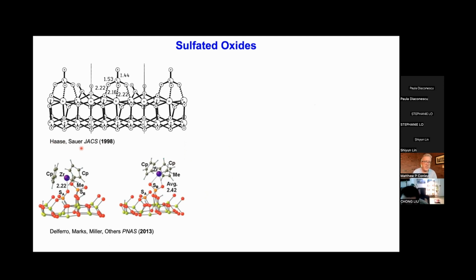And really, I think the real nail in the coffin started pretty early, with work by Joachim Sauer in the 90s, where he was looking at periodic models of zirconia surfaces absorbing gas-phase sulfuric acid to generate the acidic sites. What you can see here is that if you have a fully dehydrated zirconium oxide surface, you absorb the sulfate, which heterolytically dissociates the proton onto a nearby Zr-O-Zr bridge, which is satisfying because sulfuric acid is a strong acid and zirconium oxide is a weak base. So you're really seeing that in play here.